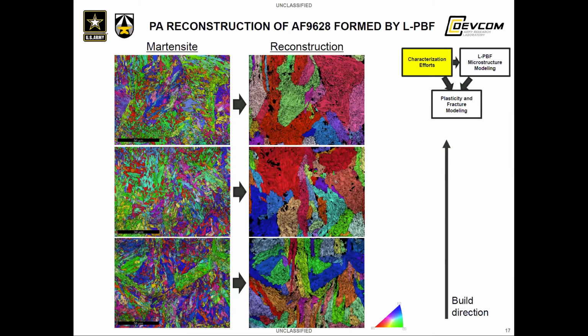The same epitaxial growth of austenite is observed with respect to the build direction, but the width of austenite grains within the cutting plane here seems to differ. The morphology of these austenite grains may not be equiaxed in the build plane either, though, and so that is an observation that still needs to be made. Ultimately, though, a lot of future work will need to be performed to correlate these structures all the way back to process parameters. Prior austenite reconstruction, however, will provide a useful set of data as work continues on to the mechanical testing and the development of plasticity models for AF9628.